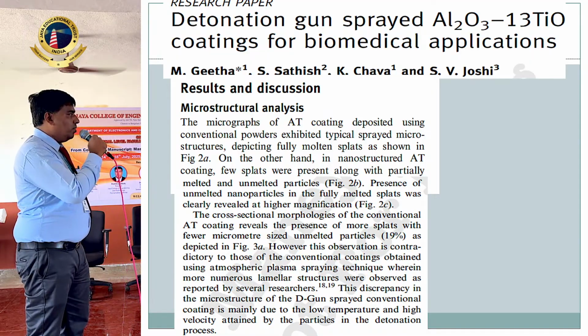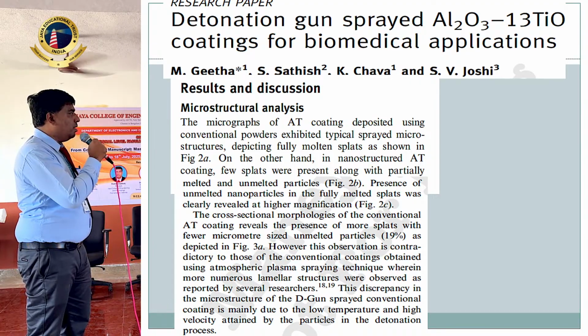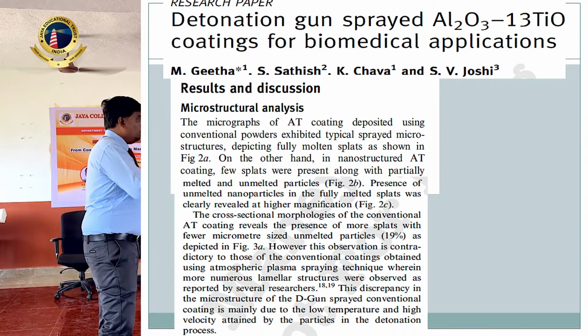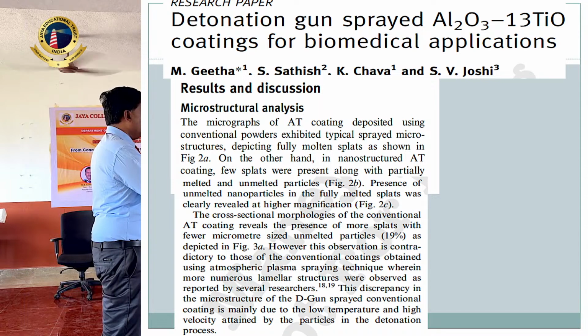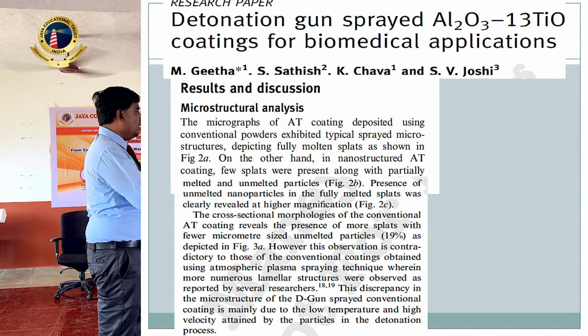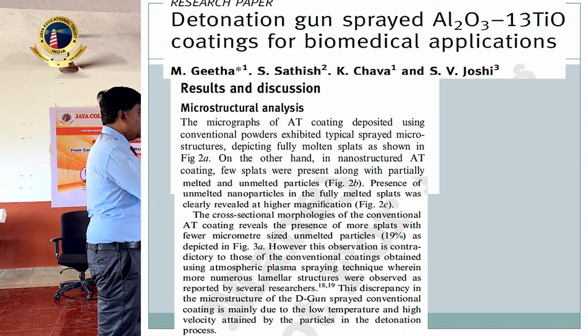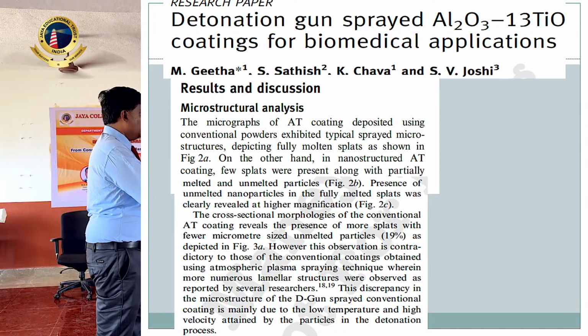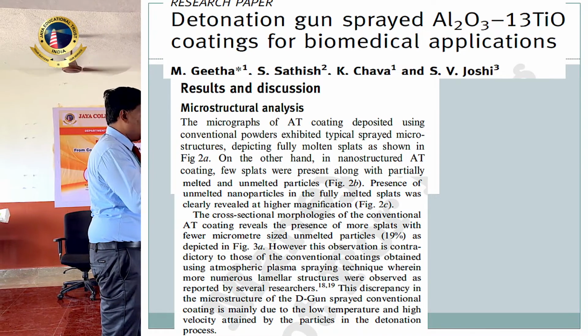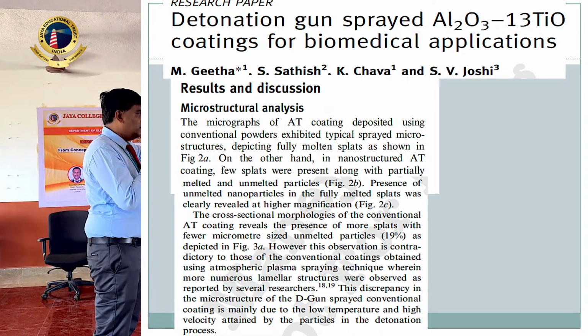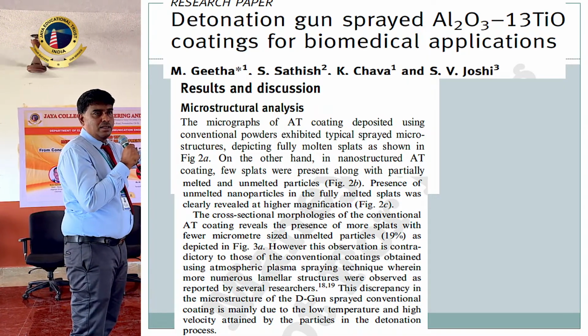The micrographs of AT coating deposited using conventional powders exhibited typical sprayed microstructures depicting fully molten splats, as shown in the figure. On the other hand, in nanostructured AT coating, few splats were present along with partially melted and unmelted particles, Figure 2b. Presence of unmelted nanoparticles in the fully melted splats was clearly revealed at higher magnification. So these are the results. I never discussed what is the reason for that.